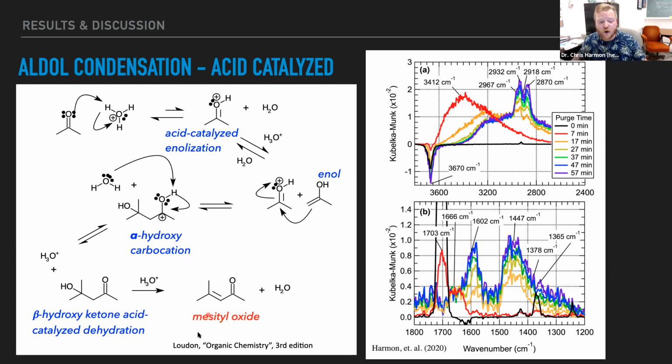And it is confirmed that the double bond of this peak occurs around 1600 wave number. So that's pretty cool that we're seeing the creation of carbon-carbon bonds. And that's important to what we want to study here, okay? Because we're interested in this creation of some organic layer around the surface, right? And as these small molecules like acetone start landing and sticking, this is what's going to make them stick irreversibly, is going through this type of chemistry.